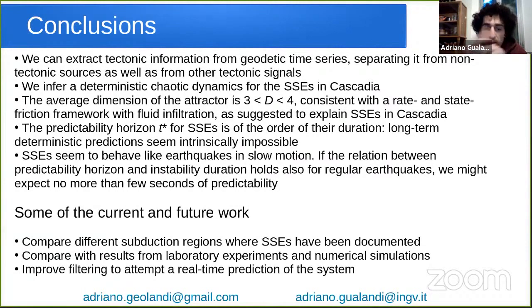Then the predictability horizon is of the order of a fraction of, or of the order of, the duration of the instability event. So long-term prediction in a deterministic sense seems to be not possible, and a statistical approach seems to be the most reasonable and the best one we can have. If we follow the analogy with regular earthquakes, and if we think of the instability time scale of the earthquake, that is just a few seconds, this also means that a long-term prediction seems to be not feasible, and so this could help only to have a few seconds of predictability for these kinds of events.